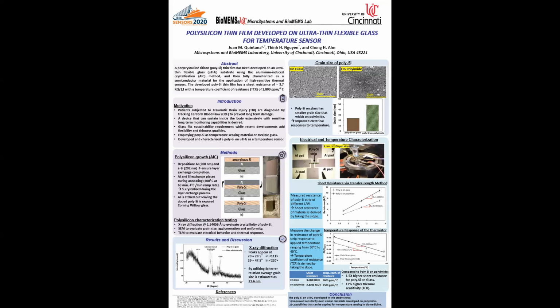Transfer length method, or TLM, was used by placing an etched polysilicon strip on a probe station and measuring the resistance of different length to width ratios to calculate the sheet resistance. Finally, by sweeping the temperature from 30 to 45 degrees Celsius, we measured the thermal response of the material. Overall, polysilicon developed on glass shows higher sheet resistance and improved thermal sensitivity of 12% over its polyimide counterpart. Interesting capabilities that can be applied in biomedicine.